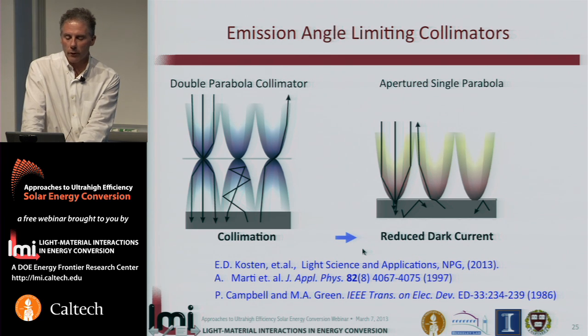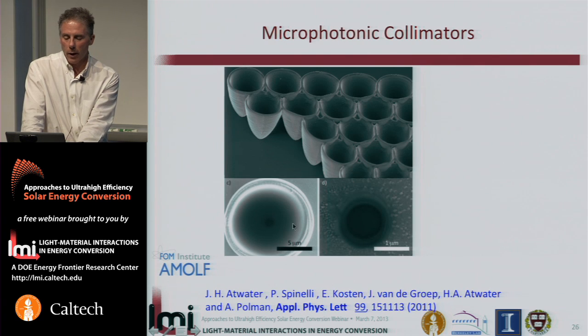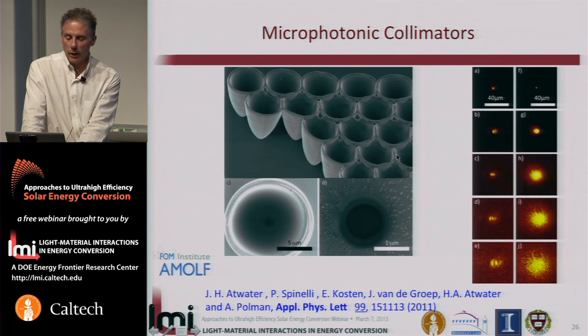And we've begun experimenting with ways that this could be done by microscale fabrication, and this depicts the fabrication of microphotonic collimators made by a prototypical fabrication with 2-photon lithography. And this leads to collimation. You can see light coming out at various heights above the surface of the collimator, which is quite highly collimated compared to a bare hole aperture in a thin film.